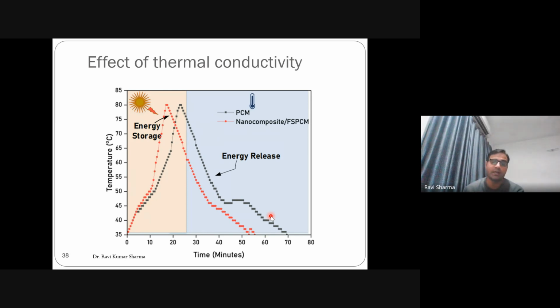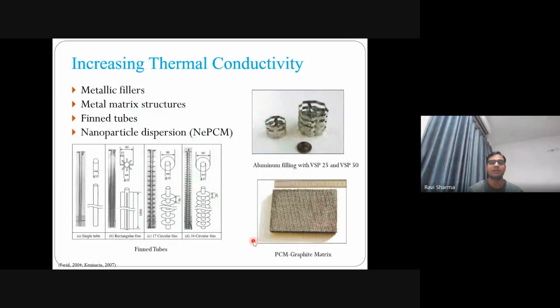Now, if I add some nanoparticles into these materials, I know its conductivity should increase. If its conductivity increases, the entire melting and freezing time should be lesser than the pure PCM time. That's what happens here. If you follow the red line, the entire melting and freezing cycle takes roughly 55 minutes. So there is a reduction of 15 minutes after addition of nanomaterials, or by developing a form-stable PCM, from 70 to 55 minutes. That is the effect of high thermal conductivity.